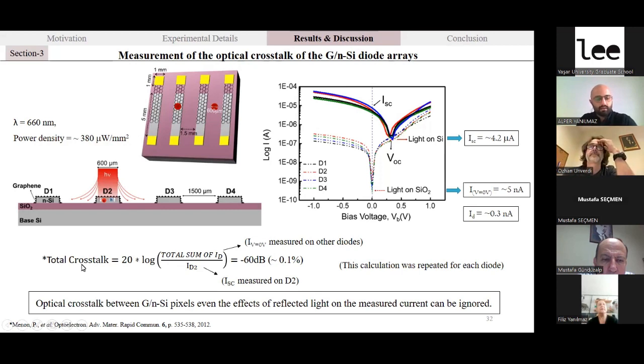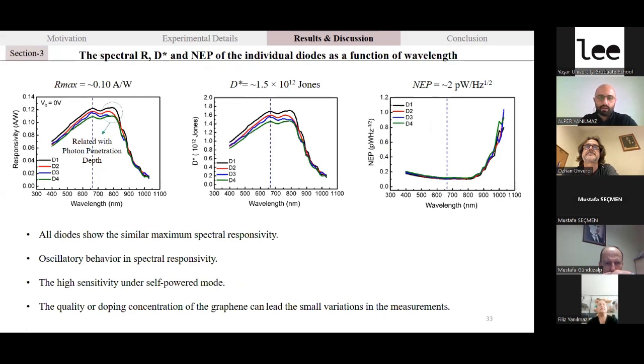However, to get the total crosstalk result, we observed nearly 0.1% crosstalk is obtained for both detectors. We concluded that optical crosstalk between each pixel, each diode array, even the effects of the reflected light on the measured current, can be ignored. So this is a very, very important result for our experiments.